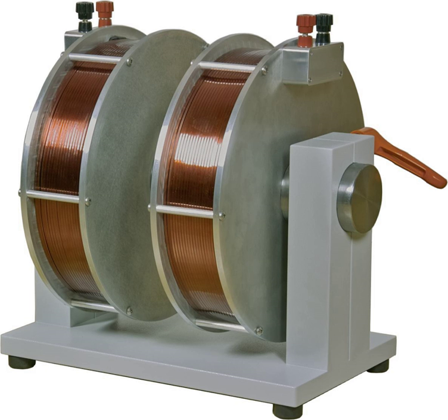Hysteresis losses. Reversing the direction of magnetization of the magnetic domains in the core material each cycle causes energy loss, because of the coercivity of the material. These losses are called hysteresis. The energy lost per cycle is proportional to the area of the hysteresis loop in the BH graph. To minimize this loss, magnetic cores used in transformers and other AC electromagnets are made of soft, low coercivity materials, such as silicon steel or soft ferrite. The energy loss per cycle of the AC current is constant for each of these processes, so the power loss increases linearly with frequency.